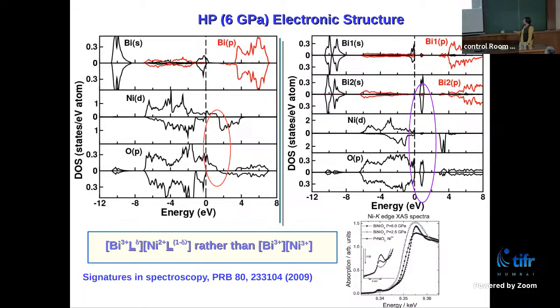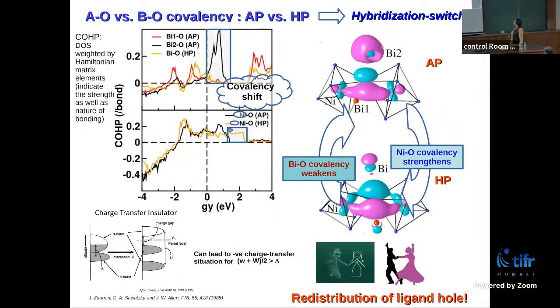So what is actually happening, and this is seen in the spectroscopy, is basically a change of covalency. I have a ligand hole. The ligand hole at ambient pressure decided to be very close to bismuth, and in high pressure, it leaves bismuth and goes to nickel. Whenever you have this ligand hole associated with bismuth, it gives rise to a checkerboard-like distortion pattern. So I have two different bismuth, one bismuth associated with two ligand holes and another bismuth associated with no ligand hole. And that gives rise, back to your question with the bond length, to the change of the bismuth oxygen bond length, one being long, another being short.